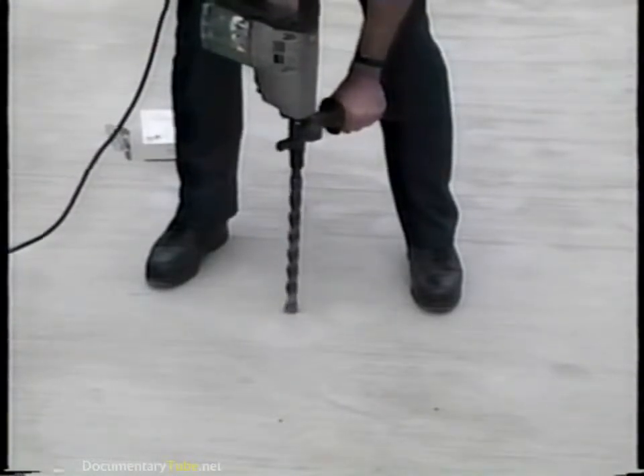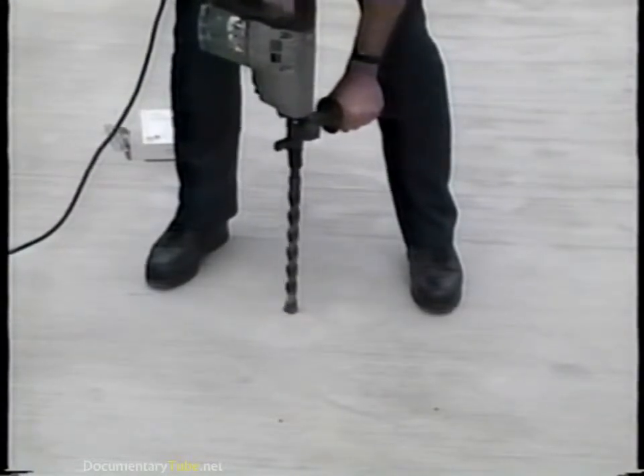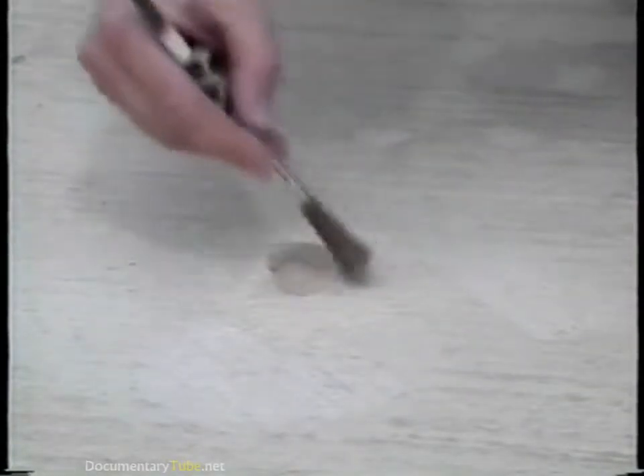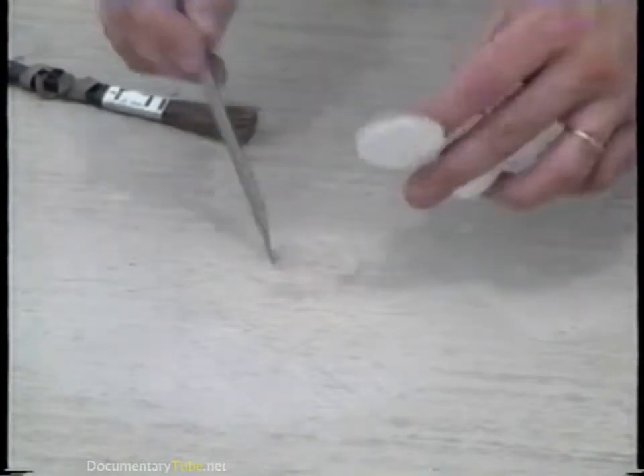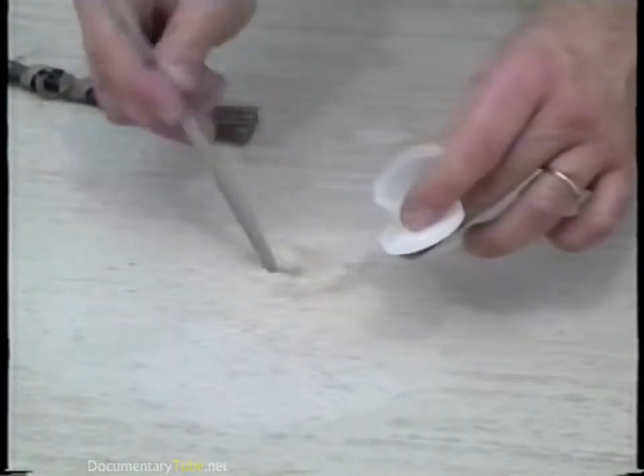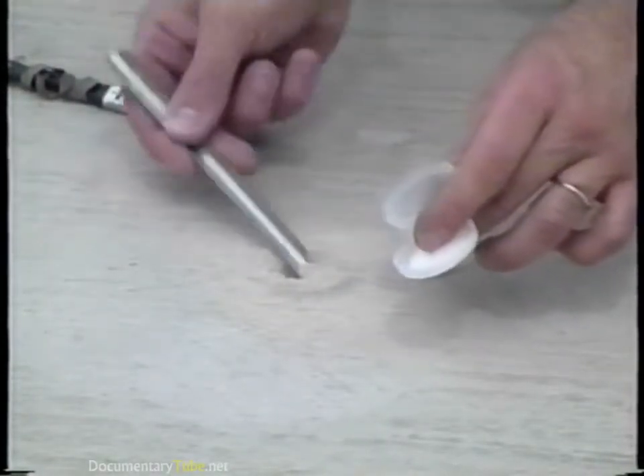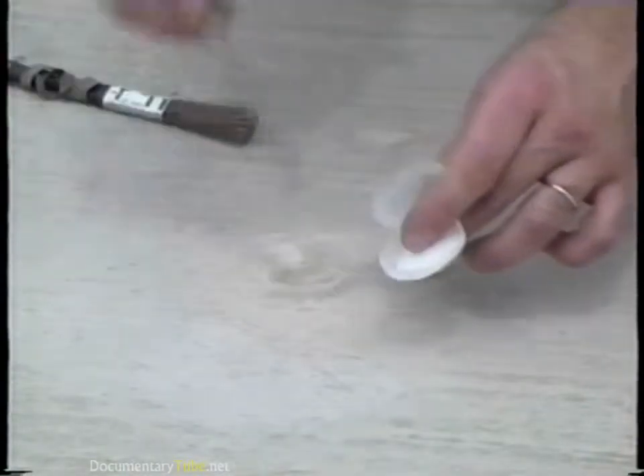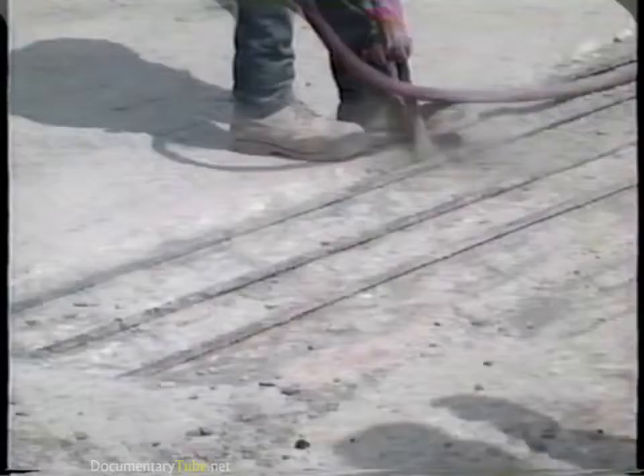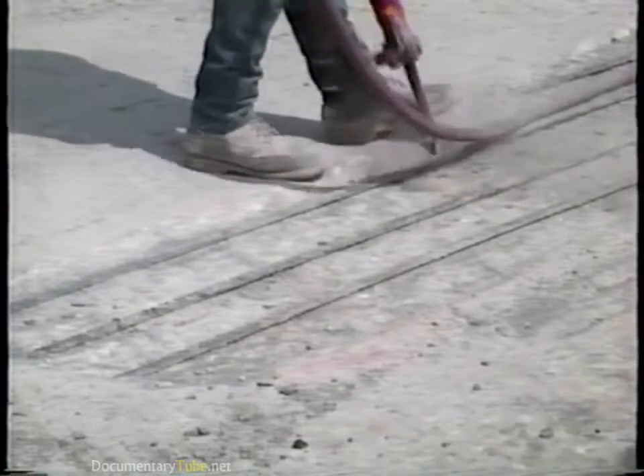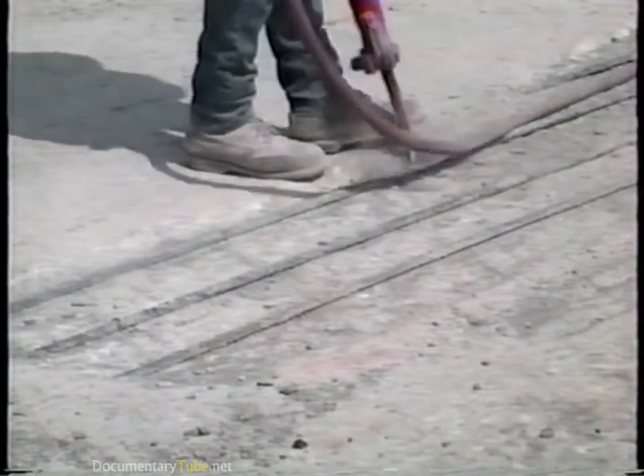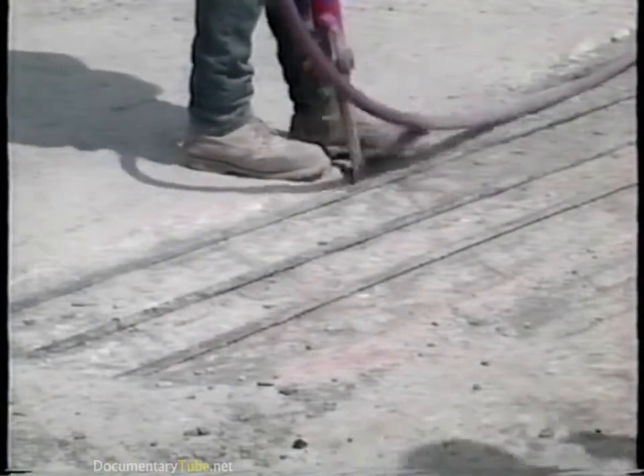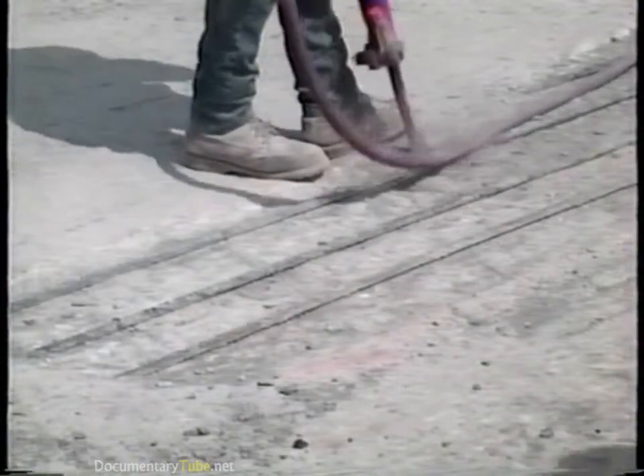Sampling for chloride analysis is another widely used measurement in deck surveys. Powder samples are obtained using an impact hammer and are then analyzed in a laboratory. Samples can also be analyzed in the field using a new technique developed by SHRP. Chloride contents in excess of 1 to 2 pounds per cubic yard of concrete are usually sufficient to initiate corrosion of rebar steel.